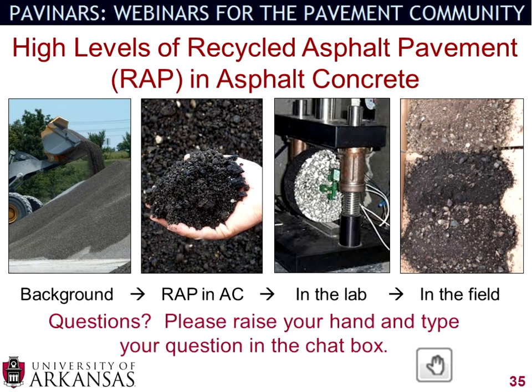And that's an excellent question, Todd, and I think that a lot of places are looking at using 100% RAP, especially in areas where you have a tremendously large amount of RAP stockpiled. And when you start getting into 100% RAP, you're starting to get into almost a cold-in-place, a CIR-type evaluation technique. I've given a couple presentations on pavement rehabilitation, and if you look at some of those flexible pavement rehabilitation presentations and look at the cold-in-place recycling, that's the sort of material you're starting to get into. And whether or not you choose to use an asphalt emulsion to bind together that CIR, or you choose to use a hot asphalt cement, I think that you're starting to look into having to deal with a material that is 100% recycled and having to really take into account how that asphalt cement on the RAP interacts with the material.